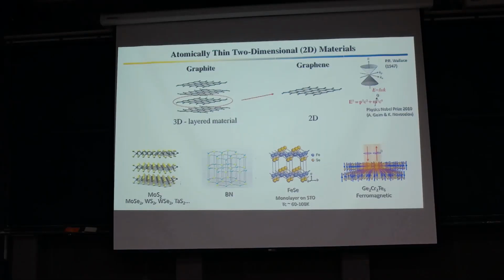Iron selenide is a very interesting material. In the bulk, it's superconducting, but if you take a single layer of this and put it on top of a surface like strontium titanate, then its superconducting transition temperature can in fact be enhanced by a factor of 10. And then we also have layered materials which are magnetic. For example, this material is ferromagnetic. And our experimental colleagues have now made single layer or few layer samples of all these materials and are able to show that the properties of these materials, when you get down to a few layer level, actually can dramatically change and give you very interesting phenomena.